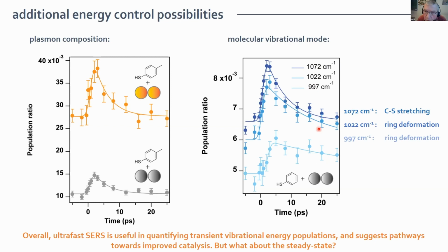Yeah, so some sort of time required for the vibration to thermalize with the other degrees of freedom, and that would depend, of course, on the coupling. Exactly, right. So many times we see sort of 10. But what it means is that it's really far away from a Boltzmann distribution. Those are not minor deviations, but really massive disturbances. Exactly, and that's why we've sort of shifted. In our earlier work, we called it temperature and effective temperature and applied a Boltzmann distribution.